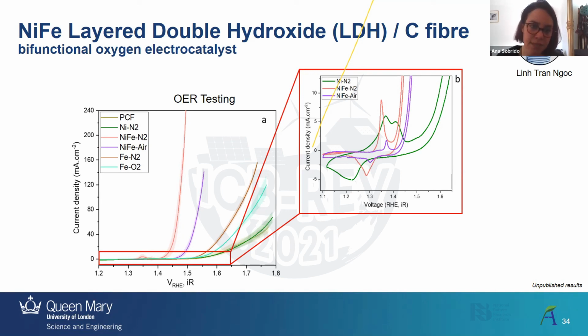So here we have results of the testing. And I just want you to focus on the hydroxide that's been prepared under flowing nitrogen, and the hydroxide that's been produced under static air. You can see it's a massive difference in overpotential and in performance. So this was quite intriguing, because we thought something might be different, but we didn't think it was going to be so different. And then here, if we zoom into this area, we can even see a little bit more the peaks that correspond to the nickel